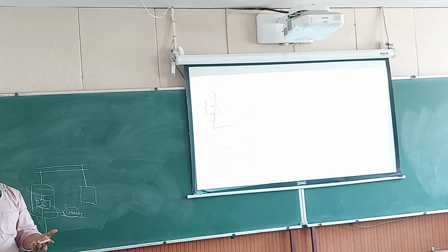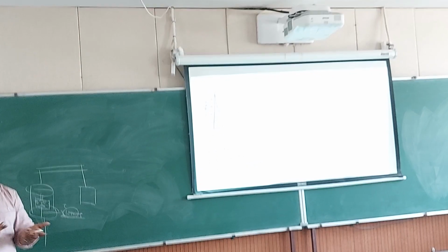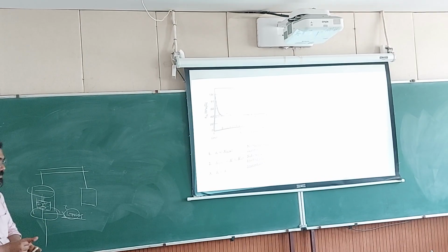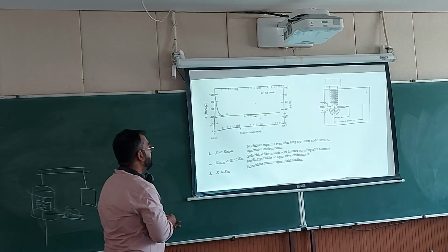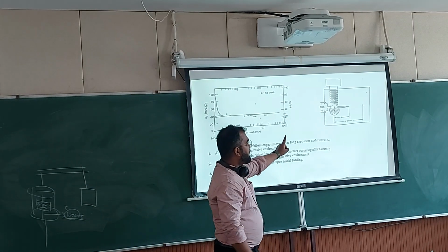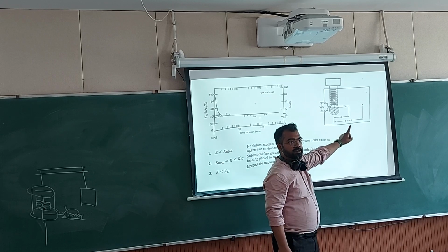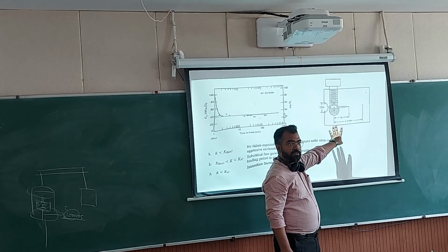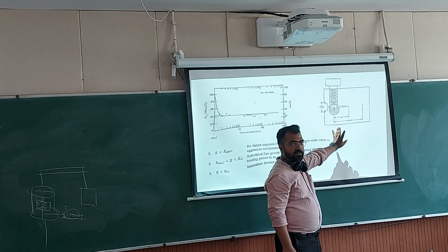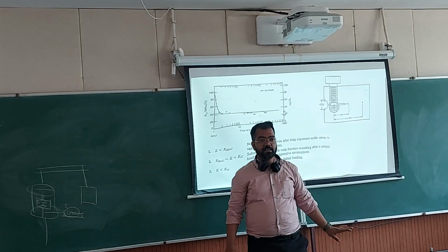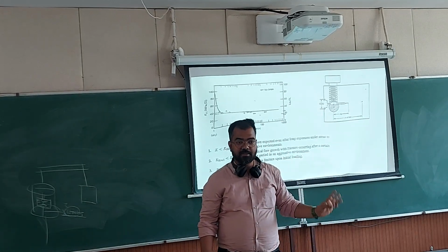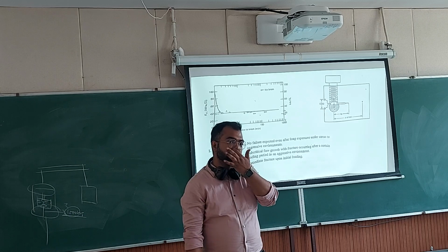Because every sample will have its own chemical structure, its own heterogeneity, so segregation of inclusions and other things. Okay, so why that sample? Because that sample can tell you the threshold value with one sample. You don't need many samples there, and this is a very easy test. Okay, and we should do it at some point of time.